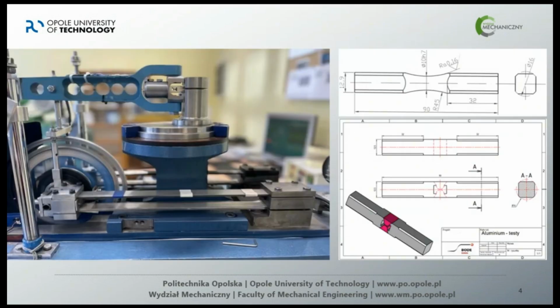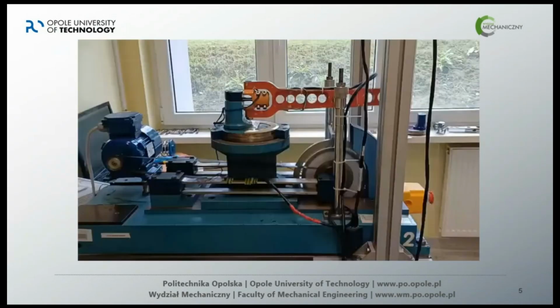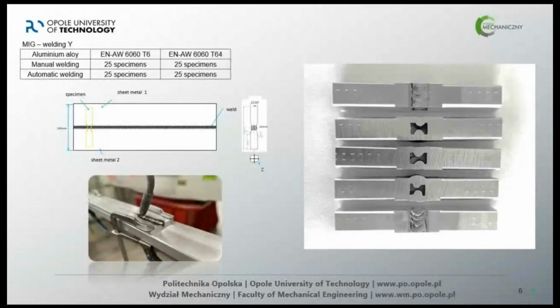Now we see the test stand, and on the right hand, at the top, the specimen without notch. Below we make a welding specimen. Here we use a mixed system: manual welding and automatic welding. Every time we use 25 specimens for the fatigue test.